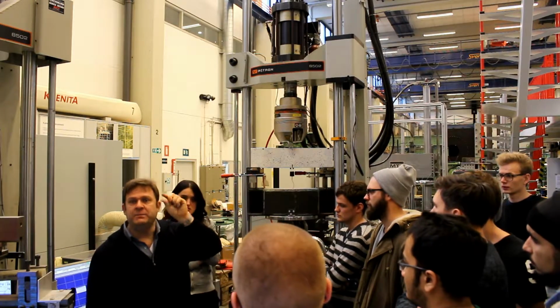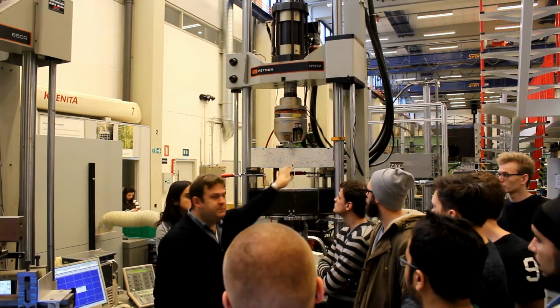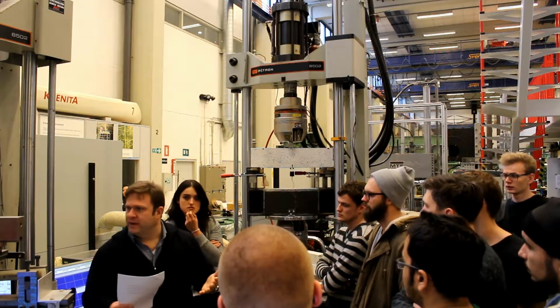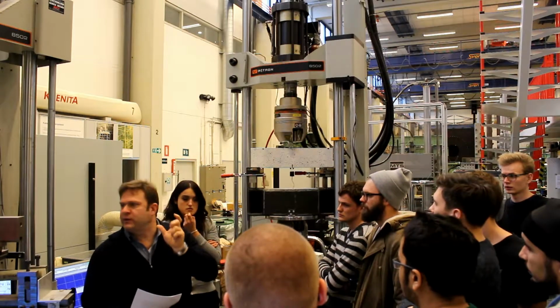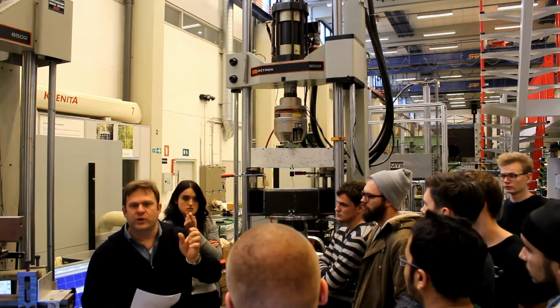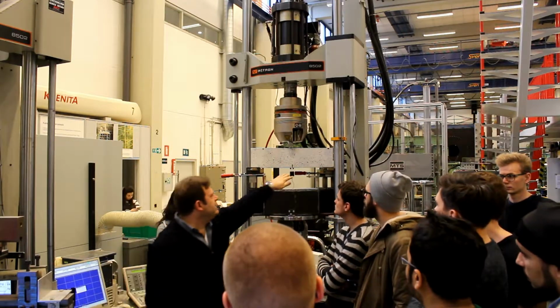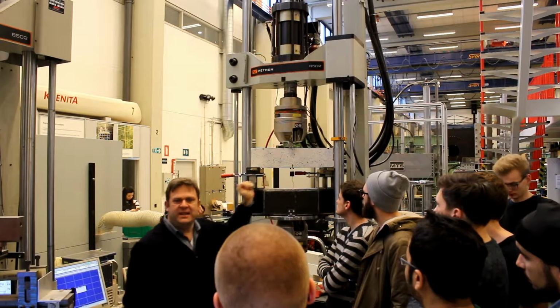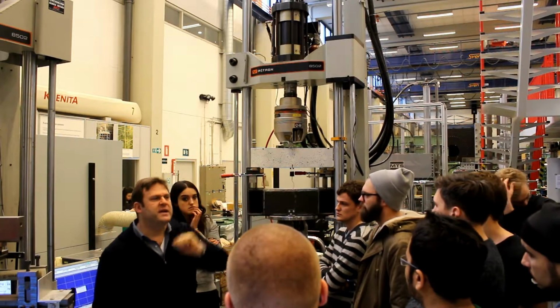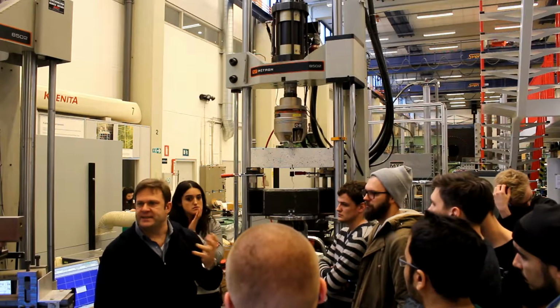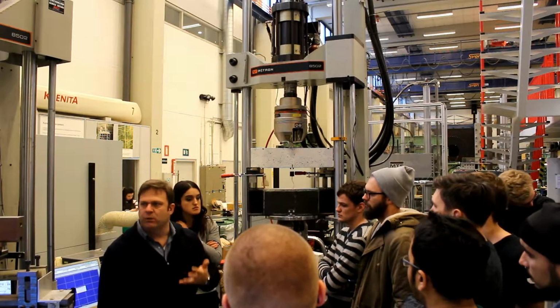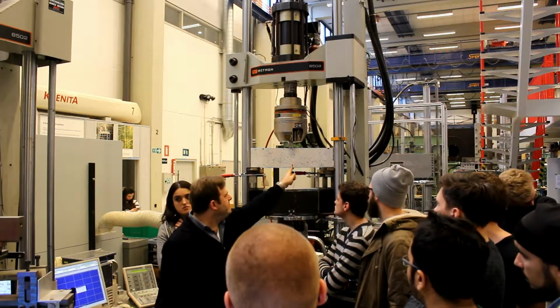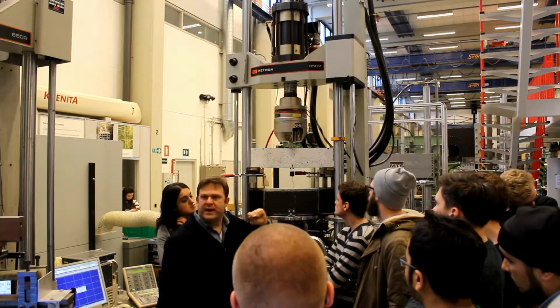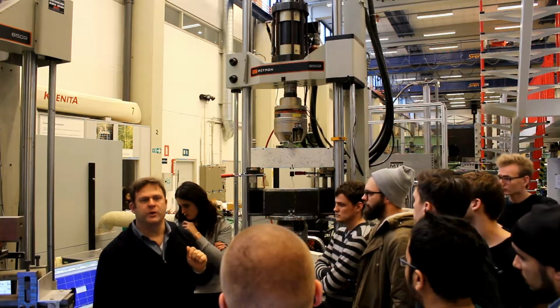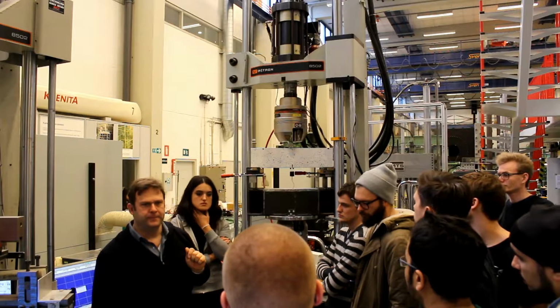Extremely slow, because this beam is quite stiff, right? So it will not deflect a lot before the crack opens. The crack occurs very, very early. You might not even be able to see a deflection when that crack occurs. So the first sign of a deformation that you will recognize, if you come very close, is a crack protruding upwards from the notch.